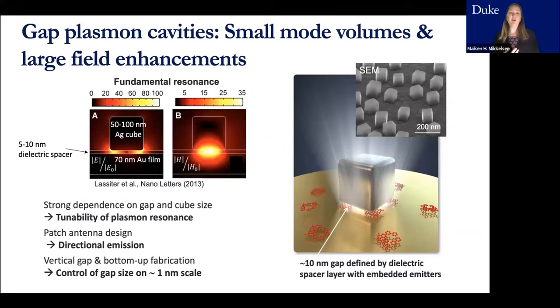The geometry that we're utilizing throughout these experiments is these gap plasmon cavities that have a small mode volume and large field enhancements. You can see the structure schematically here, and the field enhancements on the left. They consist of these colloidally synthesized nanocubes that are between 50 and 100 nanometers. So we can pick the size pretty precisely. They're very monodisperse in size. And then they're placed on top of a metal film, often gold, but it can also be silver or other materials. And then we create a small gap here that consists of a dielectric spacer that can typically be between 5 and 10 nanometers.